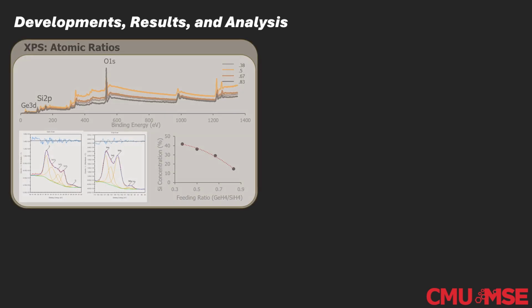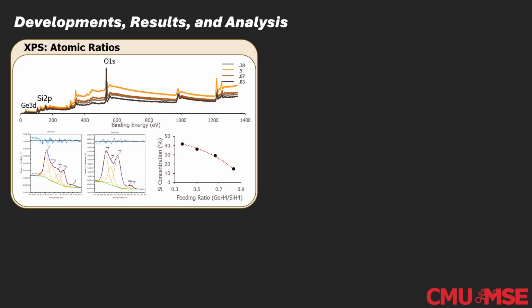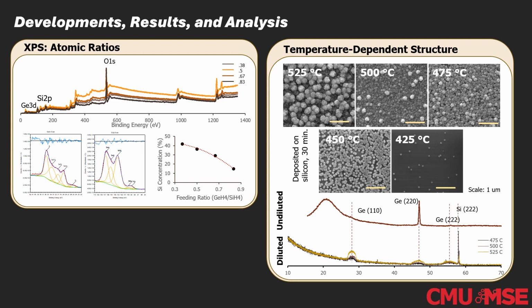The first step in evaluating this structure was to determine to what extent silicon and germanium were forming an alloy and what their morphology was. What we found was that through the manipulation of precursor gas flows, we could control the final composition of the film, determined through the deconvolution of silicon and germanium XPS peaks. Once we established that baseline, we began to look at the morphology. In the chemical vapor deposition of silicon germanium, germanium tends to aggregate into clusters that inhibit the optoelectronic performance of the device. So to suppress that behavior, we lowered the growth temperature and introduced hydrogen dilution to push towards bulk amorphosity, indicated by both the SEM and grazing incidence XRD characterization.